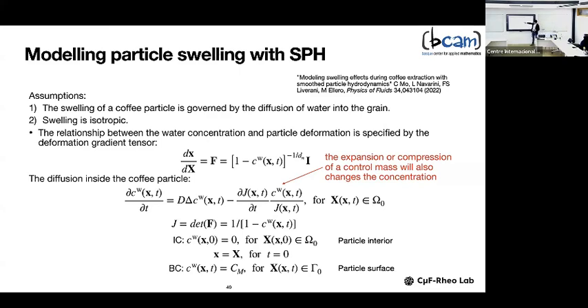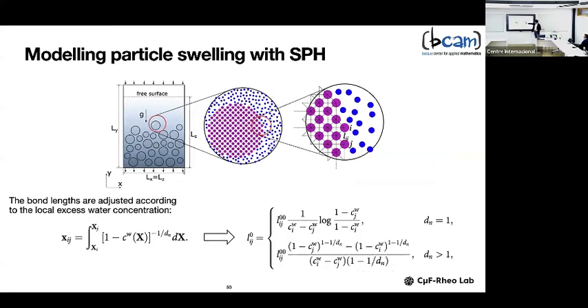If you take this deformation and you map an advection-diffusion equation into this domain, which now has a kind of swelling or ballooning effect, the effective diffusion equation that you have to take into account is slightly modified. You have the classical diffusive terms here, plus a term which takes into account the effects of the deforming domain. This takes into account the expansion or the compression, and J is essentially related to the deformation. So we would like to solve this model with some specific initial conditions. The way we do it is, inside the coffee grain, this is the coarse particle modeled by many different SPH particles.